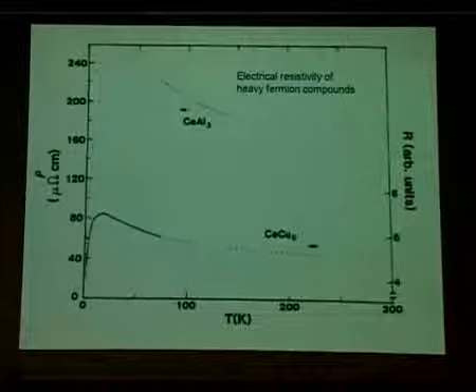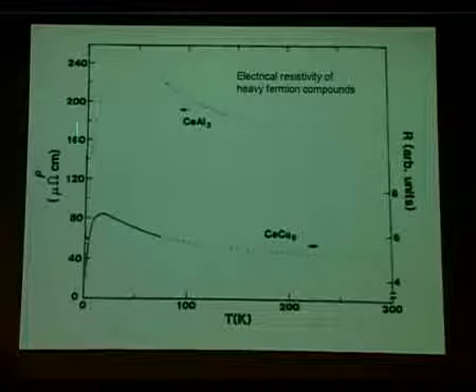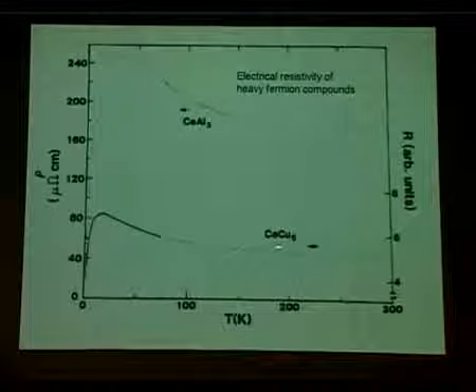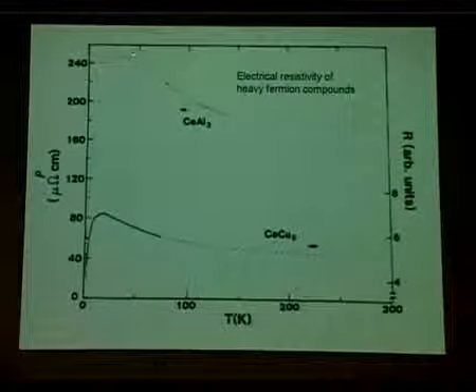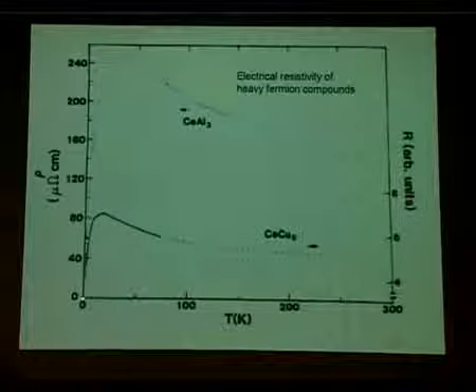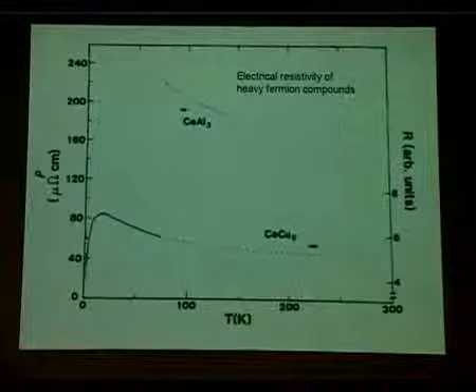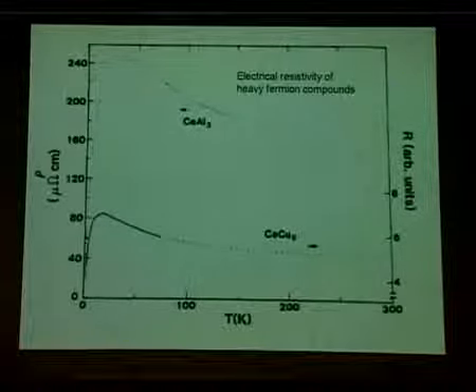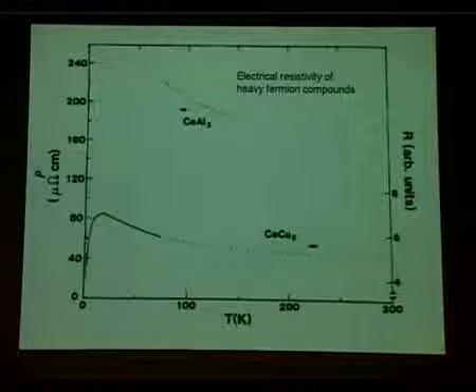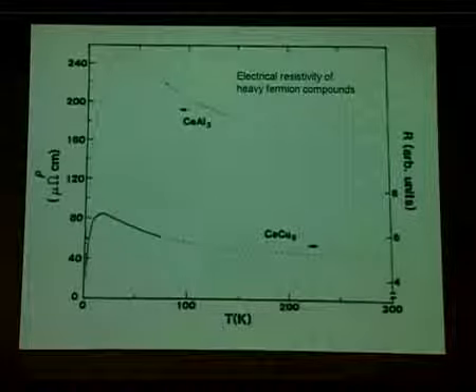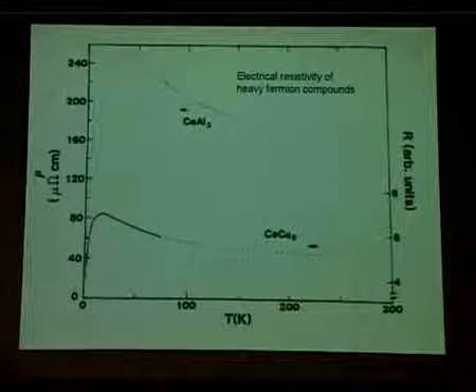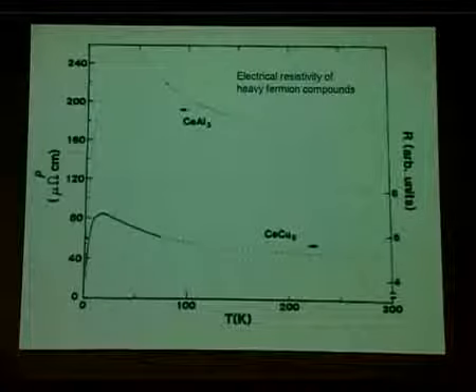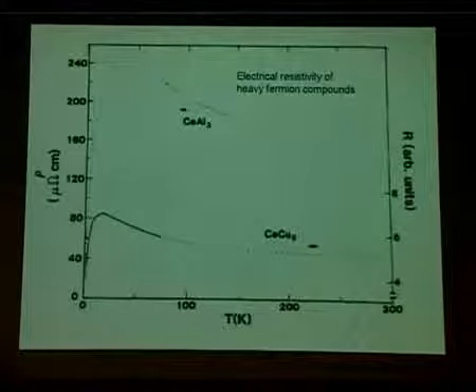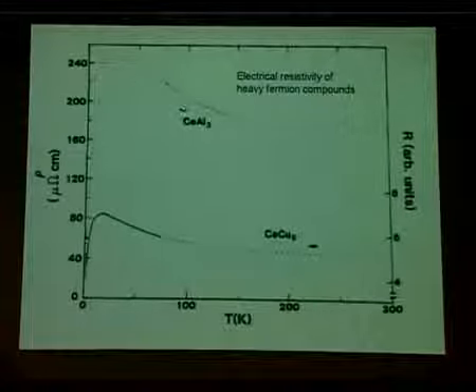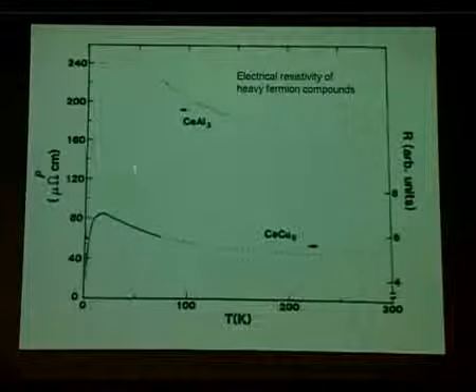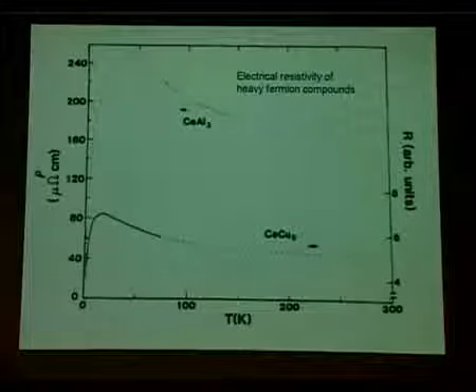Okay, so let me show some pictures. This shows the electrical resistivity of CeAl3 and CeCu6 as a function of temperature. What are we supposed to note here? Two facts. One is that the electrical resistivity vanishes at zero temperature for both of them. That is good because electrical resistivity means resistivity to the flow of electrical current. If you cool something, then all the disorder becomes less and less, and the thing is very cold, and nothing should randomly affect the motion of electrons. Then the electrical resistivity should go to 0, and that is exactly what happens here. The other interesting thing is that the electrical resistivity rapidly rises and attains some sort of a constant value at temperatures which are pretty low, like 50 degrees Kelvin or so, in this particular case.